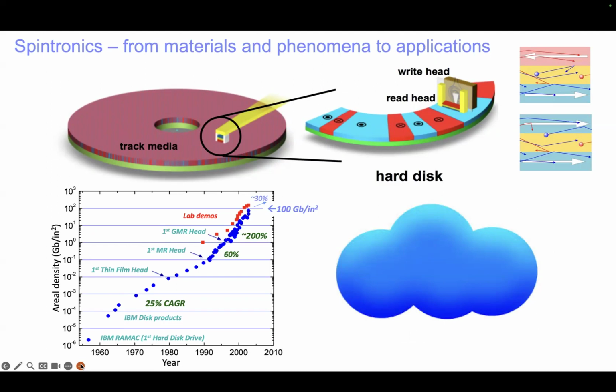So the basic concepts I invented in the early 1990s, 1989, 1990, 1991. It only took a few years before this structure made its way into a magnetic disk drive and was used to read the information by reading the fringing fields from the boundaries between successive magnetic bits magnetized in opposite directions, and the field center of the order of 10 Oersteds or so. The actual reading head during the process of reading is only 1 nanometer above the surface of this disk where it is floating on an air barrier.